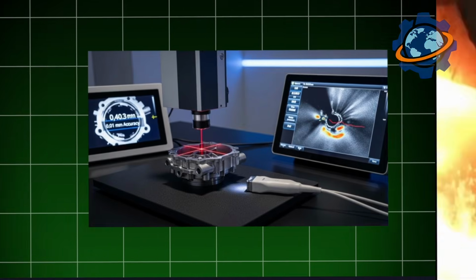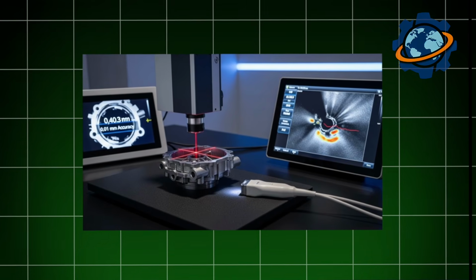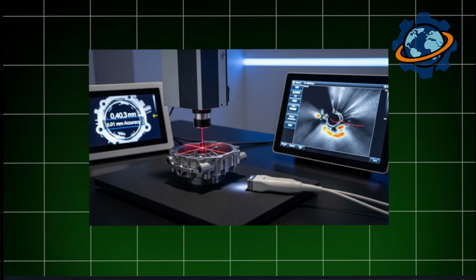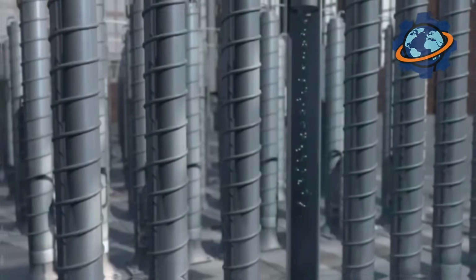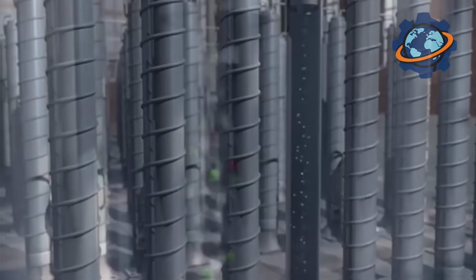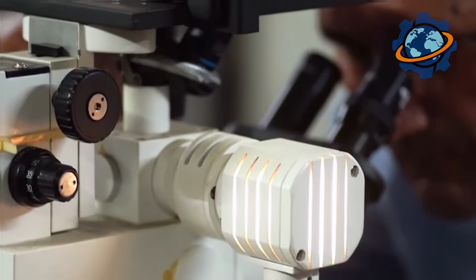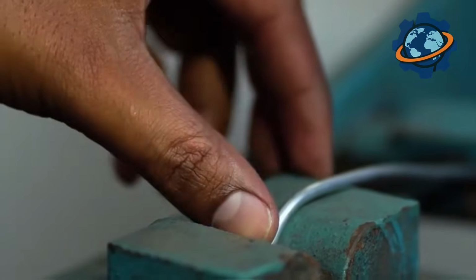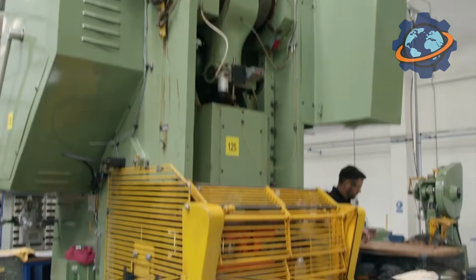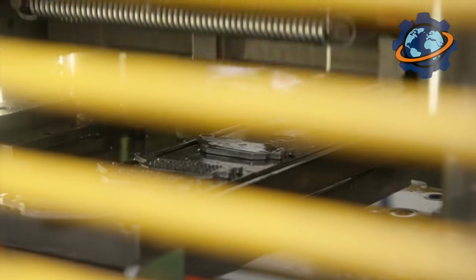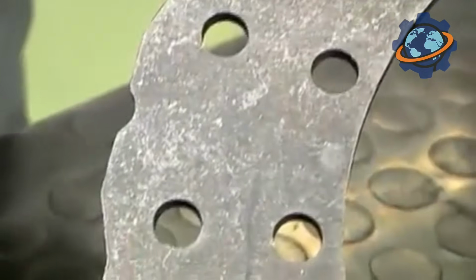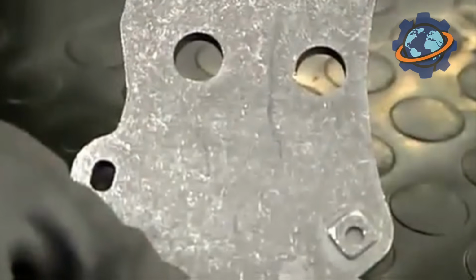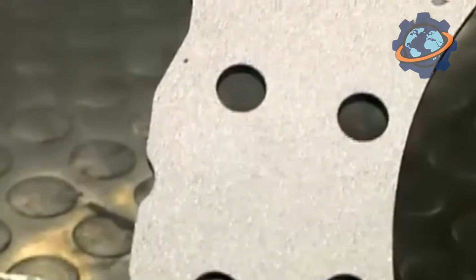A laser scanner checks dimensions accurate to 1/100th of a millimeter. Ultrasound checks density and cracks. 2% get rejected. Next, grinding. The machine removes 0.5 millimeter from the friction surface for perfect geometry. Edges get rounded to prevent squealing. They apply a protective coating, a thin layer of molybdenum disulfide for that first soft braking. Laser marked, then assembled into kits, 4 pads plus springs plus backing plate.